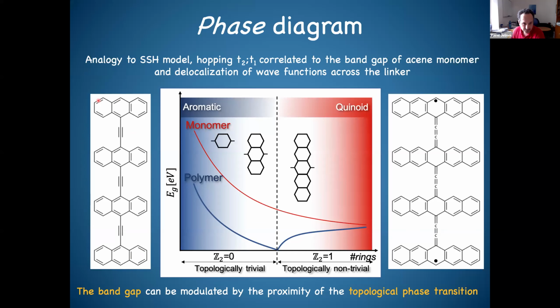Typically, if I just consider the monomers, so if I start with benzene, anthracene, pentacene, you should see in the band gap as a function of increasing units a monotonous decrease of the band gap. But I will never close it. Even if I go to the larger acenes, where there is an open question what will happen, there is still this monotonous decrease of the band gap. However, what I will show you in a minute is that if I connect these acenes and go to the polymer, I will undergo this topological transition.